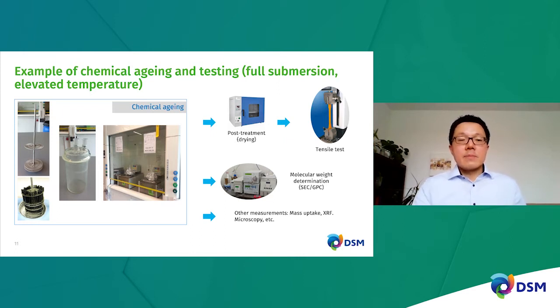After a certain period of aging, we usually take the tensile bar out. We do post-treatment from time to time, depending on the situation, and we do tensile tests afterwards. Molecular weight analysis is usually performed, so additional analysis is done depending on the situation. In this case, we use molecular weight analysis using size exclusion chromatography, SEC, which you may also know as gel permeation chromatography, GPC, and other types of analytical measurements such as mass uptake, X-ray fluorescence, and microscopy.